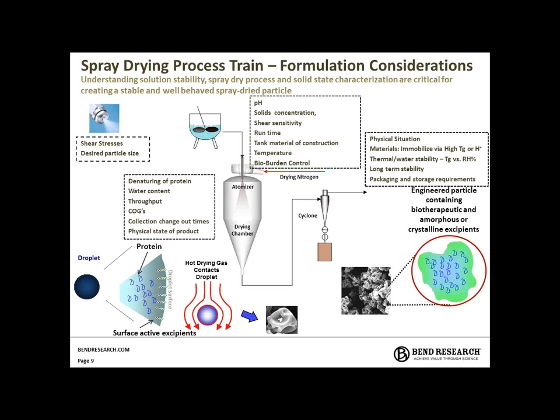Just as a simple example, we've seen issues with solution tank materials of construction actually causing flocculation or aggregation of different formulations, and we used equipment design constraints or formulation fixes to get around issues like this. Other stresses, like the shear stresses at the atomizer forming the actual droplet, or thermal stresses in the actual drying process, can be other spots where the formulation could be denatured.